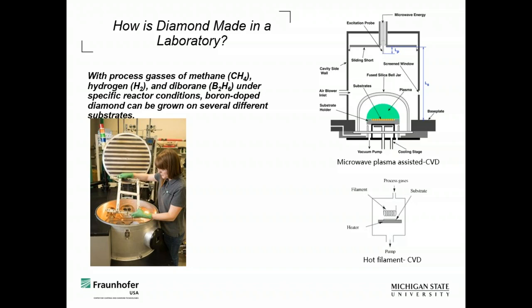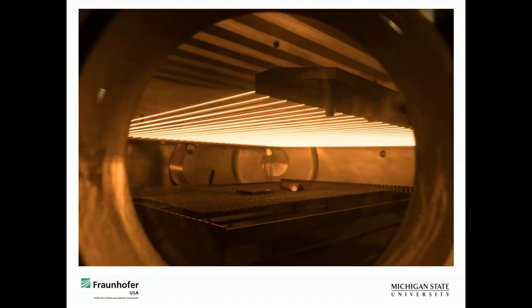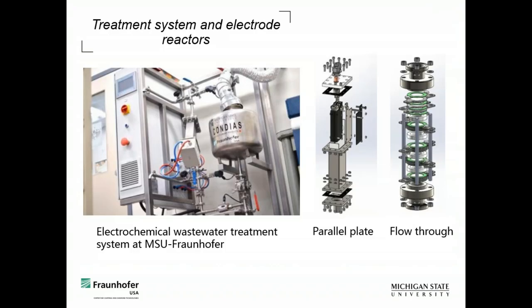We use microwave assisted CVD, but for PFAS and coating these electrodes, we use hot filament CVD, which is essentially like a gigantic toaster, which I'll show right here. So we have these tungsten filaments that are heated to well above 2400 degrees Celsius, and that's what ionizes the process gases, and then you get diamond growth down here. In this system, we could do four 6-inch wafers at once if we wanted to, but in this case, we do plates and things like that. So that's why this is a little bit more advantageous, even though the growth rates are a little bit slower.